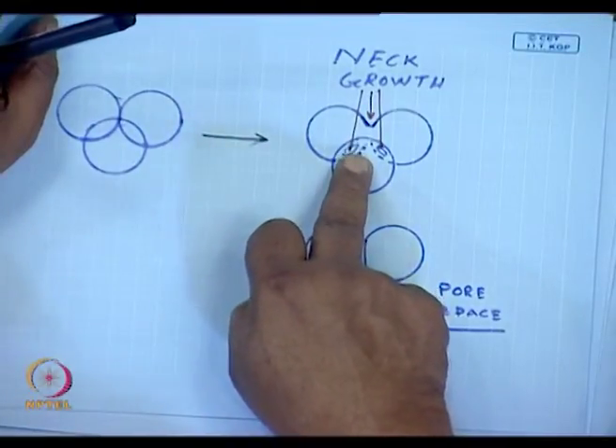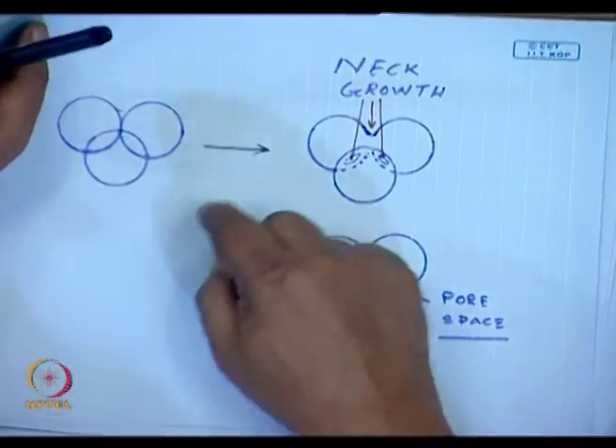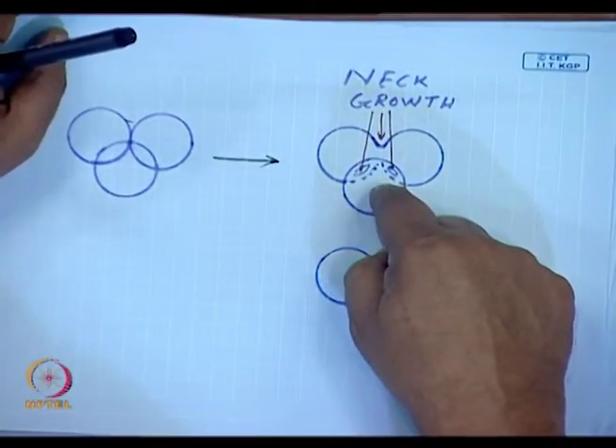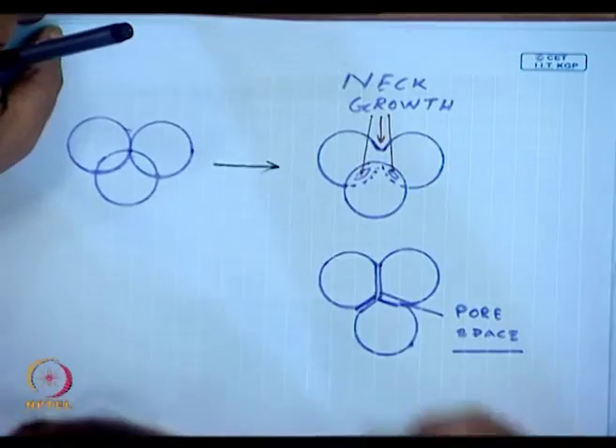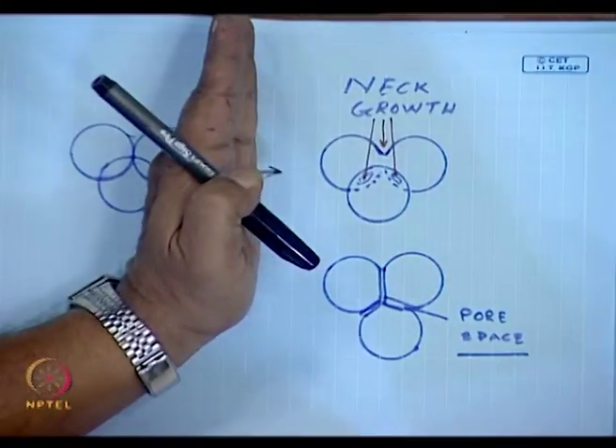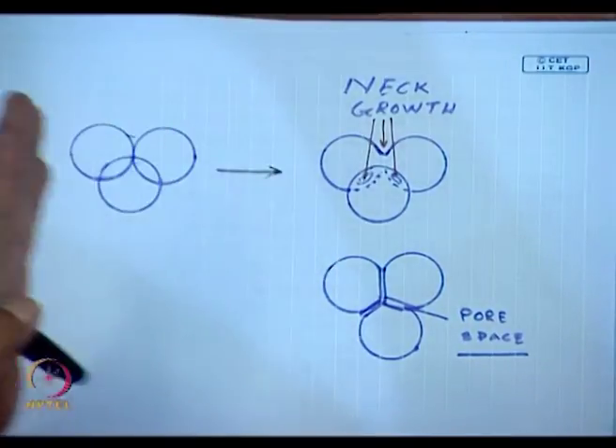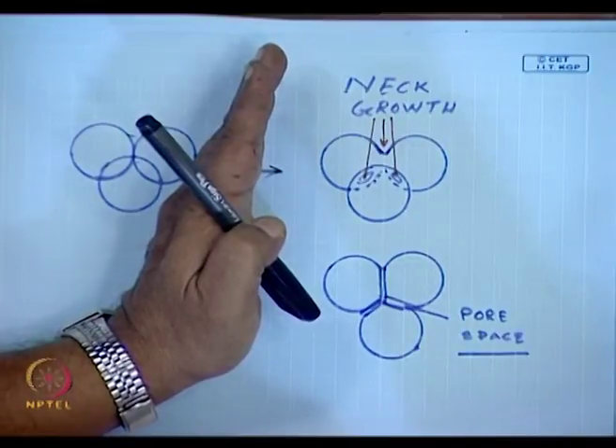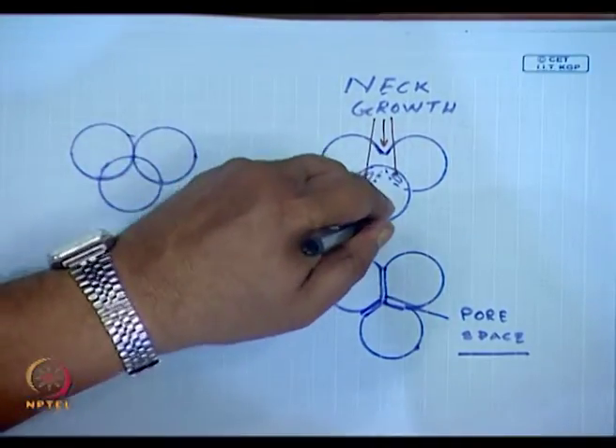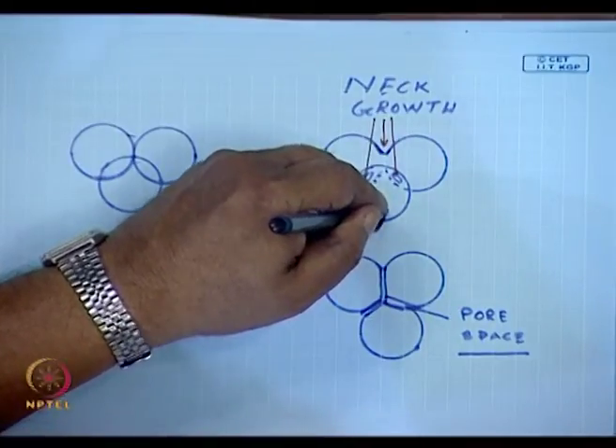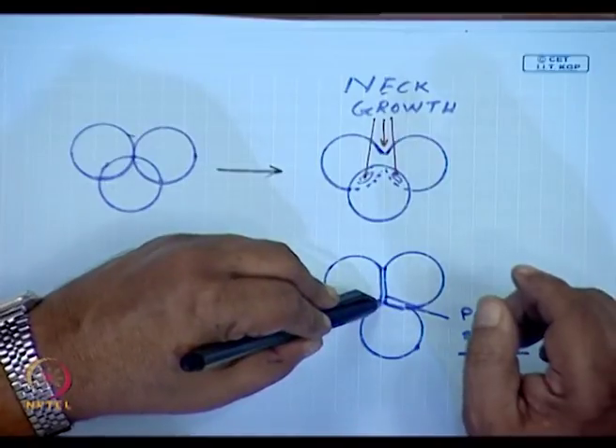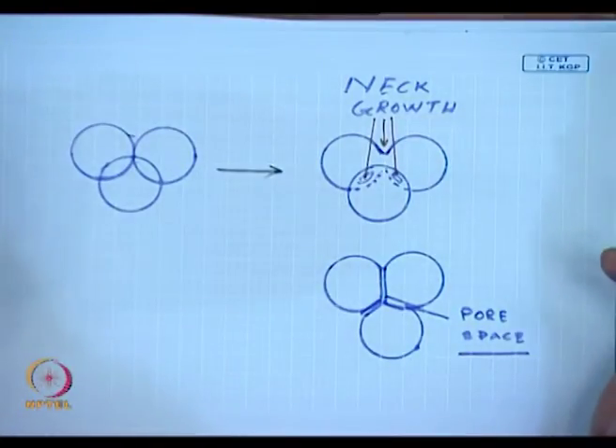During this stage of sintering, when neck growth is occurring, and even before the neck growth has occurred, we have three stages of sintering. The initial stage is when particle rearrangement can take place. This is called the second stage of sintering, because here the centers are coming together closer, leading to this particular stage, and then the final stage.